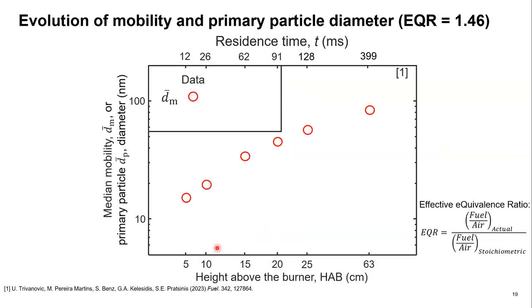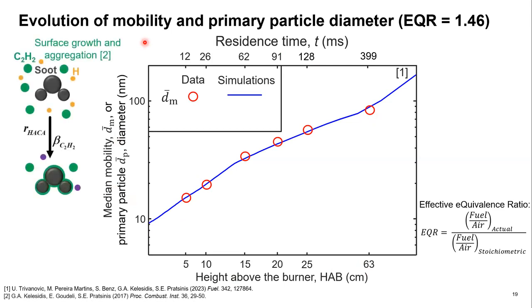So in this next slide, I have the evolution of the mobility diameter first as a function of the height above the burner and also the residence time in the flame. As we would expect, at the smallest height above the burner, we have the smallest median mobility diameter, and it continues to increase as we go through the burner. And at the exit of the flame here, this is about 63 centimeters height above the burner. We also performed simulations to better understand what was going on through this time. So I will take a moment to briefly explain these simulations, but they have been validated extensively in the previous literature that has come out of our laboratory.